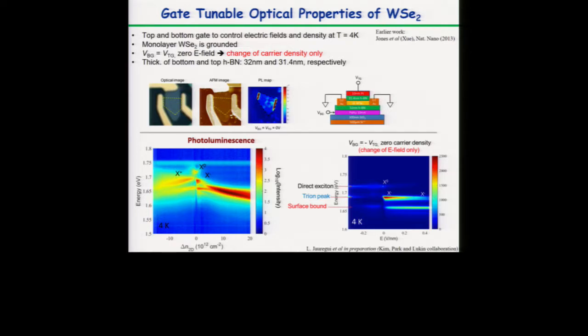What we see first in photoluminescence is this X naught, what I call the direct exciton, the charge neutral exciton. It's just an electron hole pair bound. But then once we start doping the sample, either towards N or P type, we have what is called trions. Maybe Falco won't like that when I say trions or polarons. But we have now a charged exciton because we're adding electrons or holes into the system, and now it's like a 3-particle picture.